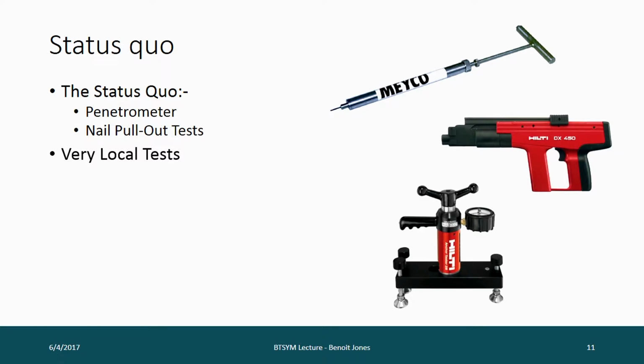And then you've got Hilti pull-out tests where you fire 10 nails into the shotcrete and you use that little jig to pull them out. So you measure the penetration distance, you pull them out. There's a lot of possible things that can go wrong with this test. For instance, at higher strengths, you're meant to use shorter nails. And if you use the longer ones, they're not always straight, and then that can actually cause a false reading.